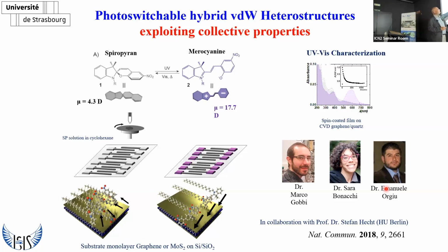I will tell you very briefly the approach of this Marco Gobbi story that we published already 4 years ago. The idea is to have a spiropyran with a very long alkyl chain. The R is a C18 chain. And so the C18 chain imposes the formation of a lamella structure, so we can control with atomic precision where we locate the spiro head group. And in these dry films prepared by spin coating, we can in situ, with irradiation at different wavelengths, switch from the spiro to the mero and vice versa.